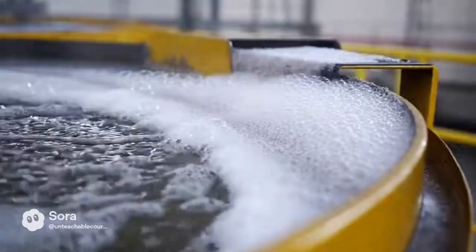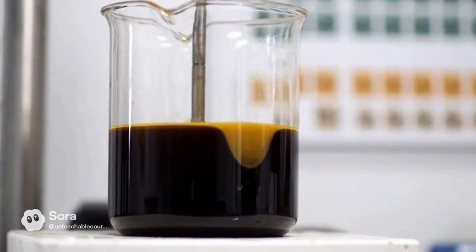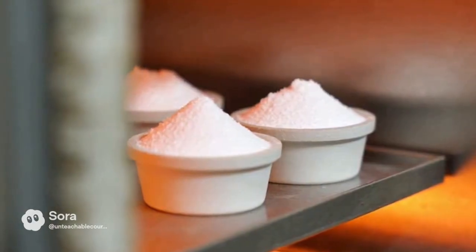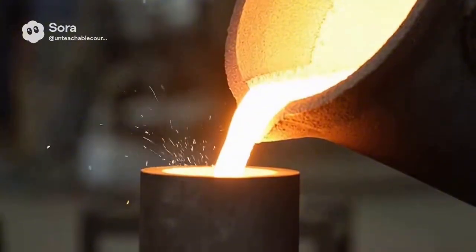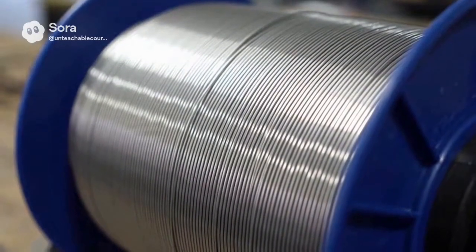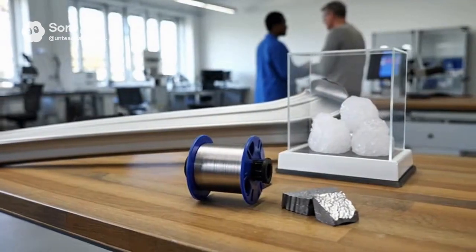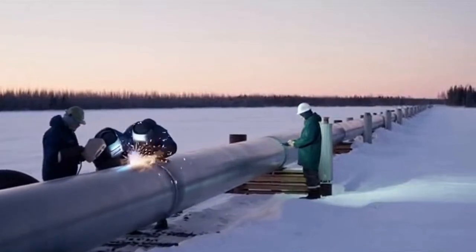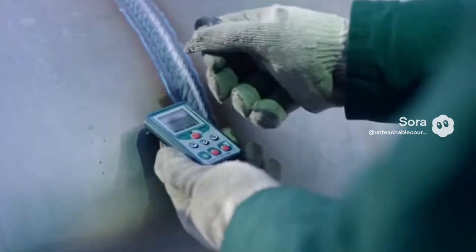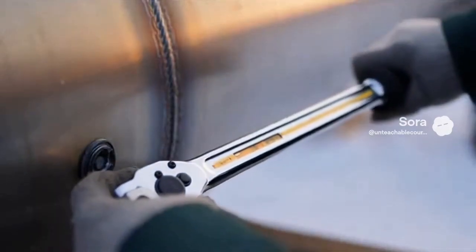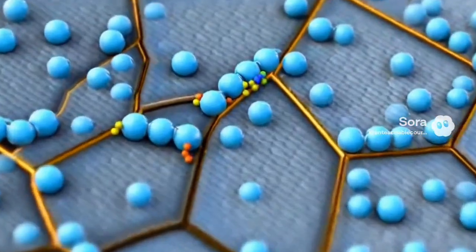If the destination is niobium metal for superconducting components, the path is fussier. Niobium pentoxide is reduced to metal, through a sequence that can involve chlorination to niobium chloride and reduction with sodium or by direct metal oxide reduction, followed by electron beam melting to achieve electronic-grade purity. It is not simply a question of how pure.